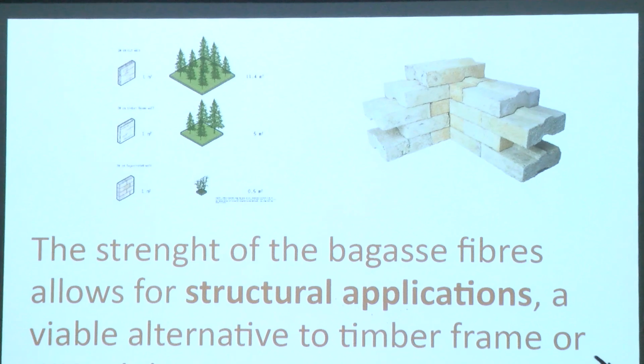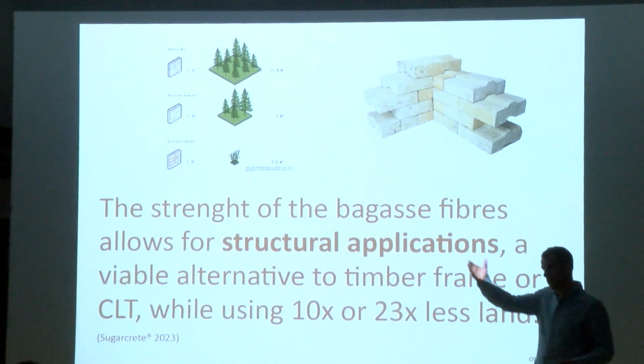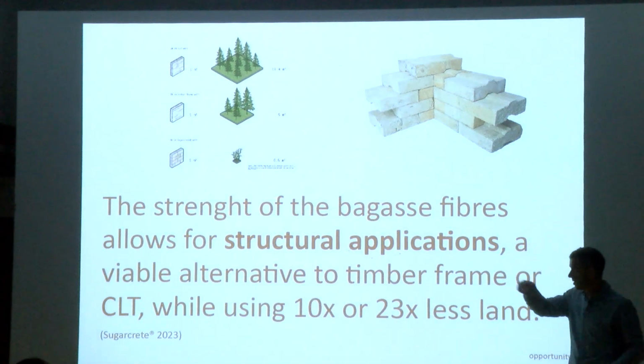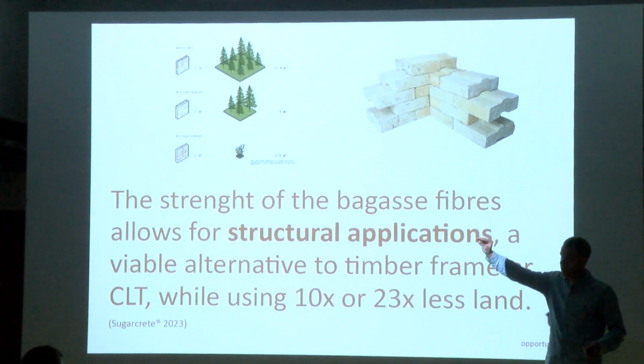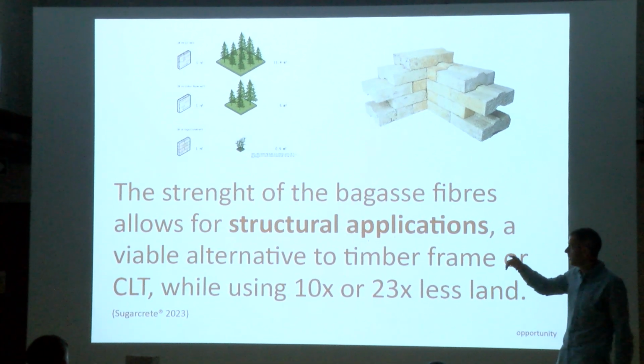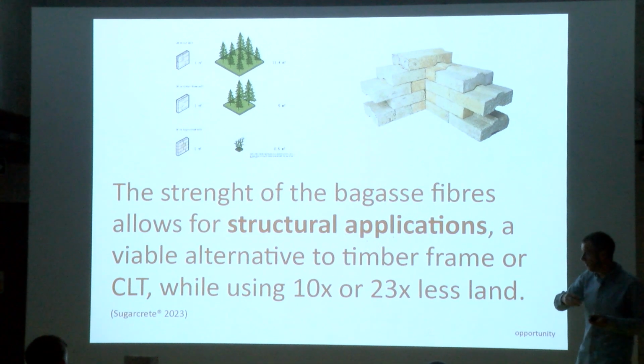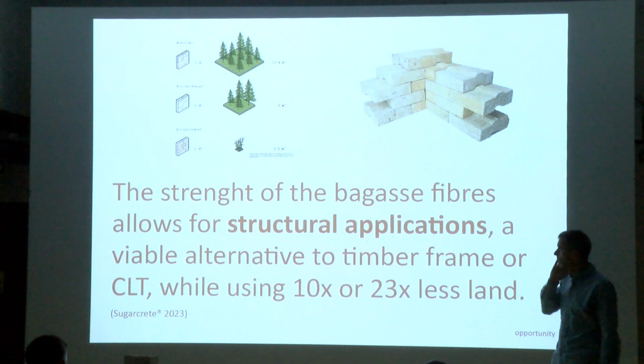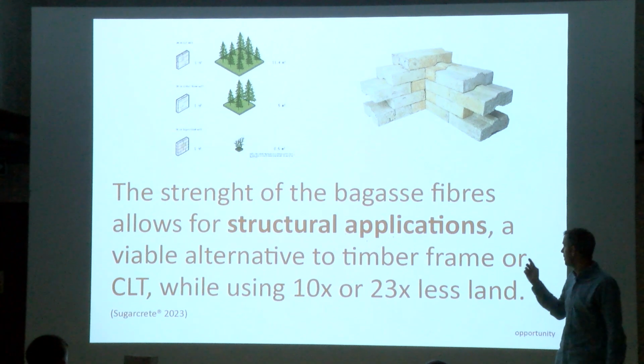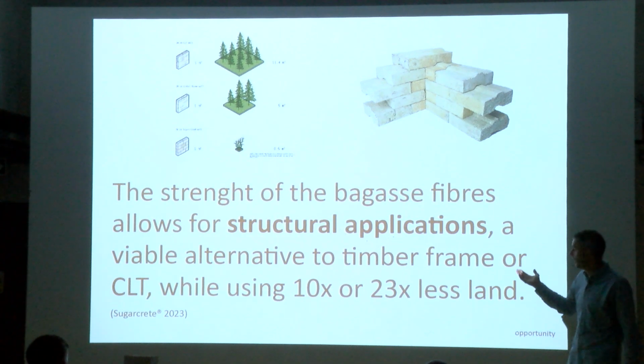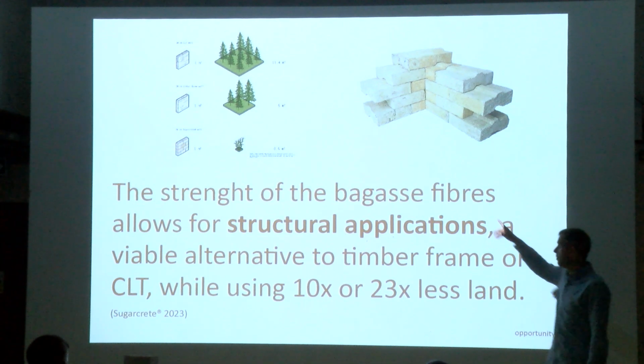The fibers of bagasse are quite long, especially after being milled. The milling process has 5 different mills which extract the sugar and the water from the plant, and the fibers that are left are quite long and they interlock each other very well, which allows for structural applications, and it can become a viable alternative to replace timber frame or CLT using much less land.